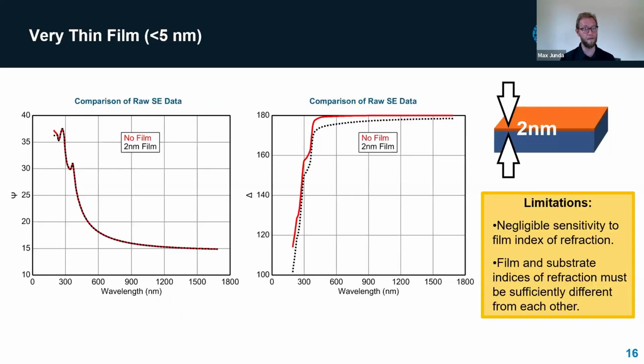Now let's look at the case of really, really thin films. So I talked about this a little bit on one of the earlier slides. Here is an example of measuring a 2 nanometer film that's on a substrate. In this case, I've simulated silicon. And so you can see these are the 2 pieces of raw data, the psi and the delta, that ellipsometry measures. And so you can see in psi, the difference between the red line, which is the case where there is no film, and the black dotted line, which is the case where there is a 2 nanometer film, is very, very small. It's just different on the far left end of the spectrum there. Whereas if you look at delta, again, it is basically just a shift, but it is definitely measurable.